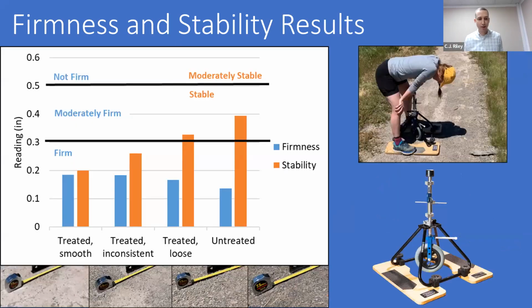So here are some of our results, working on the left from a treated and smooth surface to the right untreated surface. And you'll see we also looked at treated and inconsistent and treated and loose patches. Ultimately, the implementation was fairly inconsistent. We had areas where there was plenty of moisture. The plate compactor created a nice smooth surface that seemed to appear and remain solid for a longer period of time. There were other areas that were just rougher. They were treated, but they were inconsistent. And then there were some areas where it was clear that moisture hadn't really penetrated or been integrated as well as it maybe ought to have. And that was the treated loose material.